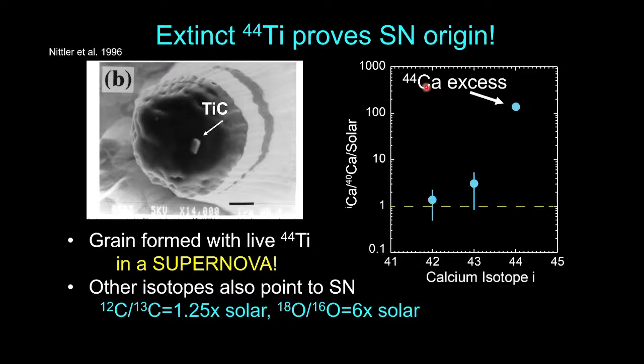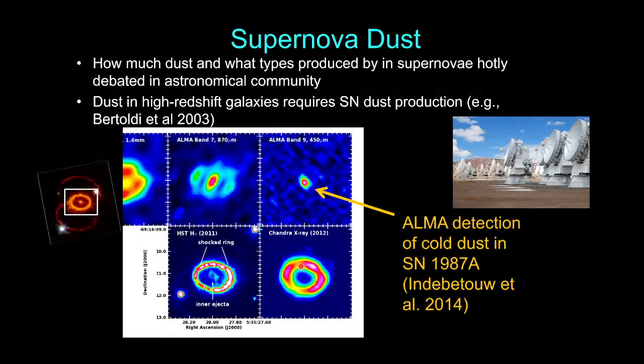In this case, this shows that this grain had titanium-44 in it when it formed. Titanium-44 is only made in supernovae, and it only lives for 60 years. So that means that's proof that this grain formed in one of these supernova explosions. The other isotopes are also completely consistent with forming in a supernova. So we also, in addition to having grains from AGB stars, we have grains from supernovae.